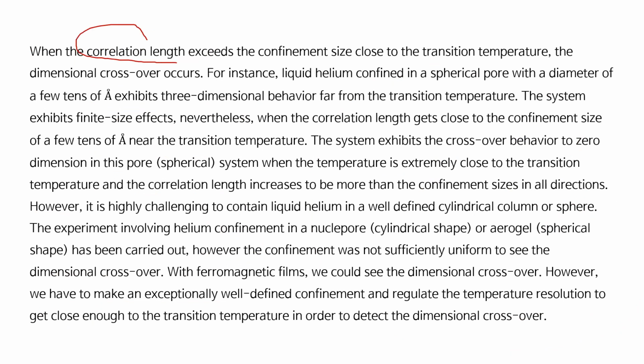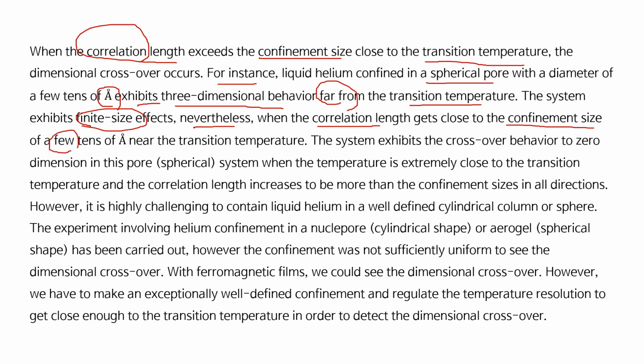When the correlation length exceeds confinement size close to the transition temperature, the dimensional crossover occurs. For instance, liquid helium confined in a spherical pore with a diameter of a few tens of angstrom exhibits a three-dimensional behavior far from the transition temperature. The system exhibits finite size effects. Nevertheless, when the correlation length gets closer to the confinement size of a few tens of angstrom near the transition temperature, the system exhibits the crossover behavior to zero dimension in this pore system, when the temperature is extremely close to the transition temperature and the correlation length increases to be more than the confinement size in all directions.